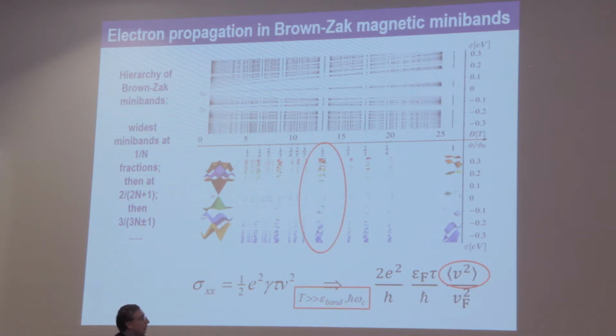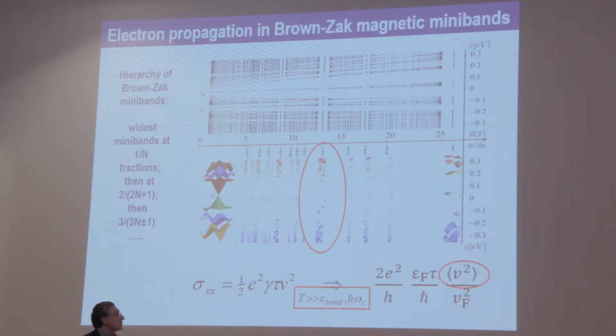The only argument that I have to put forward to use this way to describe conductivity is to say that the length at which electrons undergo any scattering at all will be more than the period of this extended period of the superlattice, the period of the magnetic superlattice, which will be several times the period of the superlattice itself if we're talking about rational fractions which do not have too large a value of n in the denominator. And this is a much weaker constraint as compared to the constraint required to be able to see the gaps in the spectrum, which is that the temperature in the system has to be smaller than the distance between the bands and the sizes of the gaps in between the bands.